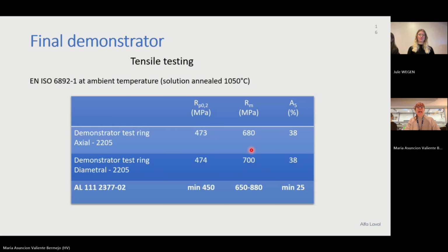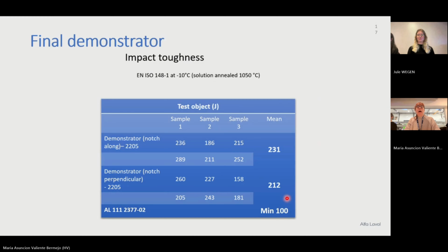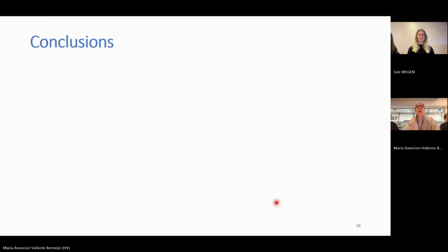Then when we look into the corrosion properties, our target values were according to Alfa Laval's standard. As you can see, the different samples in the different orientations, according to this pitting potential testing, succeeded with the requirements. So it was okay. From the tensile testing, we also test in the different directions, and all these samples also succeeded with the requirements. So that was also good. And impact toughness, we had 6 samples tested also in the different directions, and also succeeded with the minimum requirements by Alfa Laval.